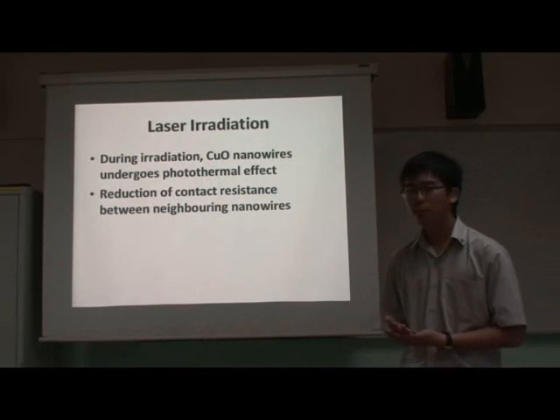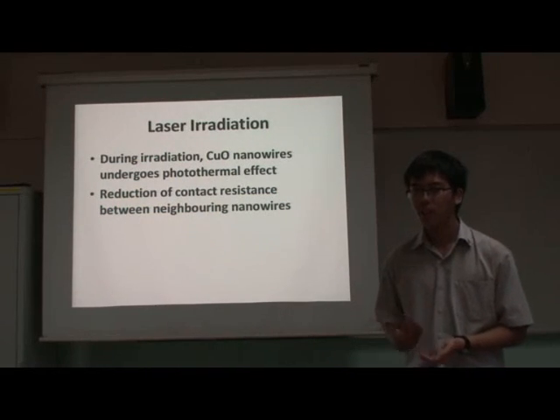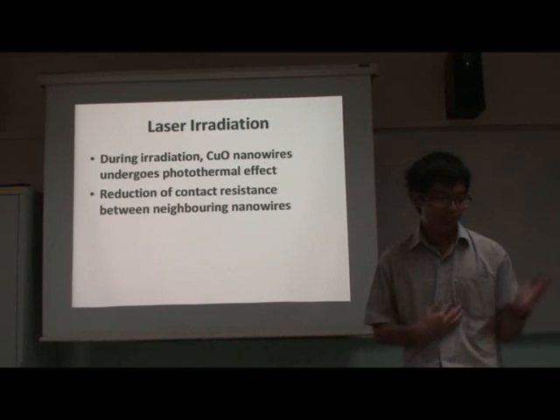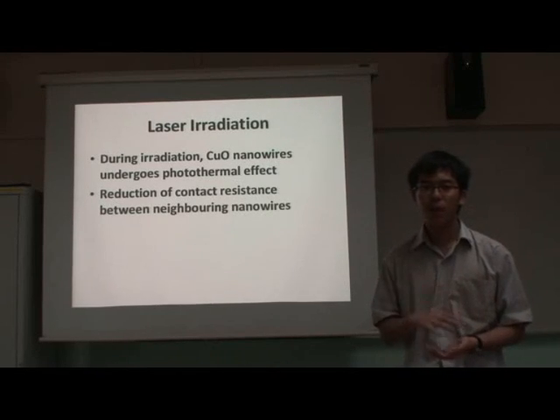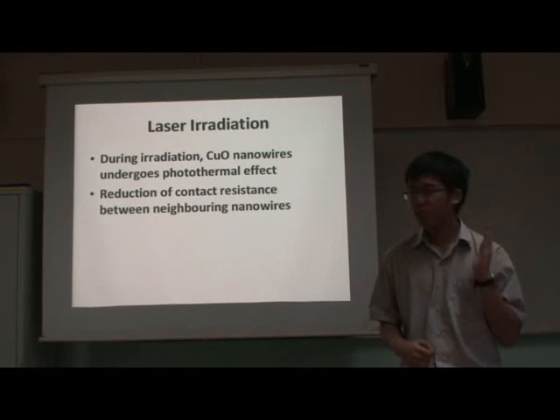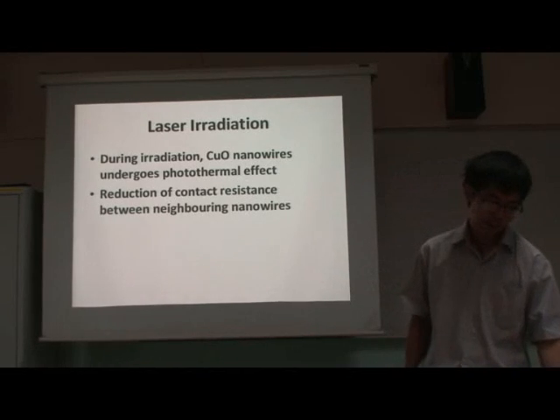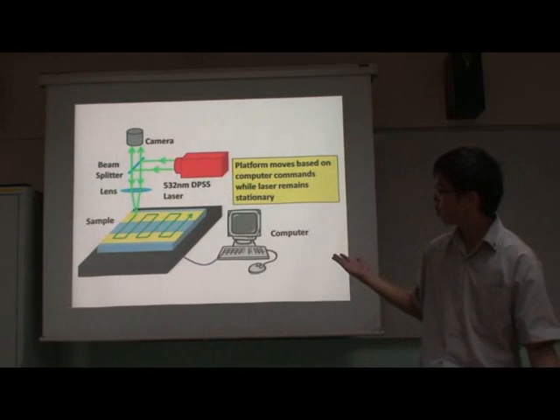After performing our electrical property testing, we will then move on to laser irradiation. What happens during laser irradiation is that copper oxide nanowires melt and fuse with neighboring wires. This actually helps reduce the contact resistance of our nanowires. So this is actually what happens during our laser irradiation.